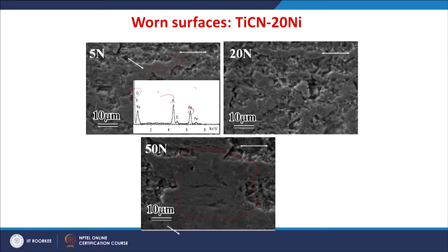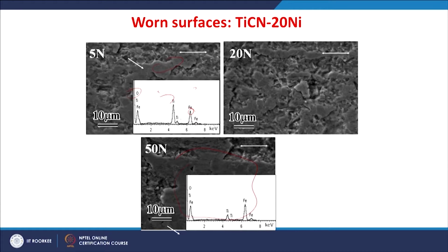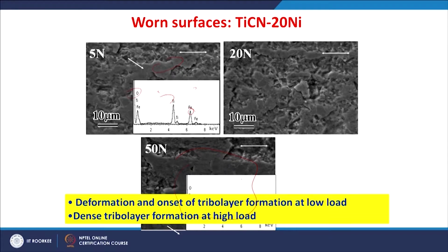The EDS analysis of this particular layer fragment shows there are oxides of titanium and iron, and at higher loads you can see again oxides of titanium and iron, but a very interesting observation is that the titanium peak is reduced, whereas the iron is increased. So, with increase in load the iron oxide content is more than the titanium oxide in the layer. So, there is deformation and the onset of tribolayer formation at lower load, whereas dense tribolayer formation is observed at the higher loads.